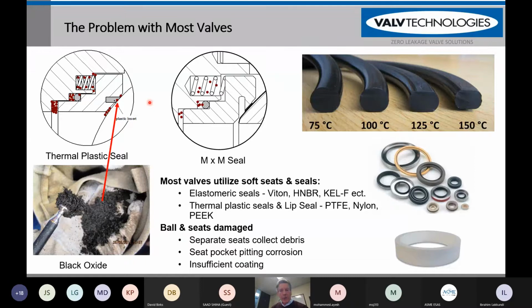In the correct service. However, when you start taking valves that are not designed for severe service applications and you put them into severe service applications, you can get debris like you can see right here. This is a typical seat for a trunnion mounted ball valve. This is the ball right here. You can see that the seat has a plastic insert. More than likely that's a grade of nylon. And you also have debris. You have a piston effect on the seat, and you can get debris buildup back behind the seat.